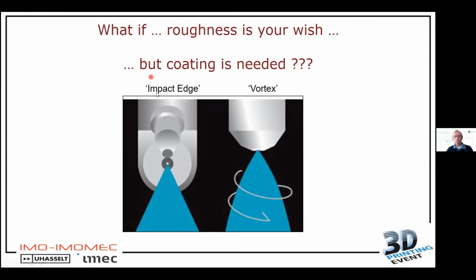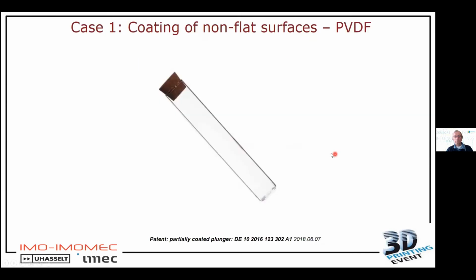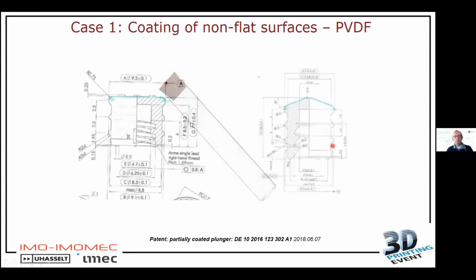We use this impact edge nozzle. But for example, if you go to the vortex, your droplets will not go perpendicular to the substrate, but will be vortexed such that they come in at an angle onto the substrate. And that can be used for different applications. For example, here we put a coating specifically only on the top of a plunger. I quickly show the results here.